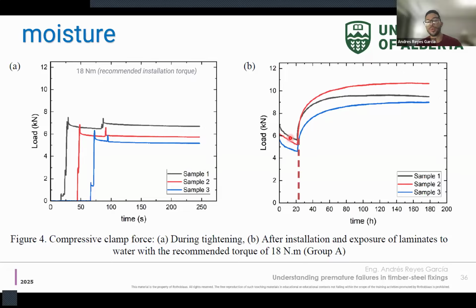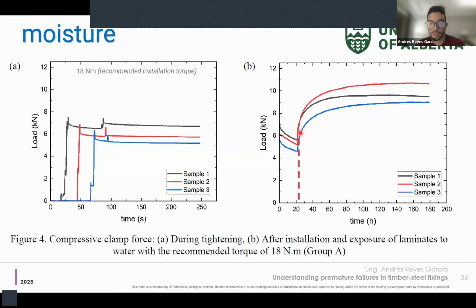And when we pour some water on it, you see that there is a big bump. If we take a look at the red curve, you see that we have an increase, it will go from, let's say, 5 to 11. So it's a lot of force that's coming from the swelling effect. Here the increase is a lot, and it's hard to say if these are two effects that can sum each other in the construction site in a real case. But if we take a look at it as a worst case scenario, then we think it is very relevant to be considered and to be studied a bit further.